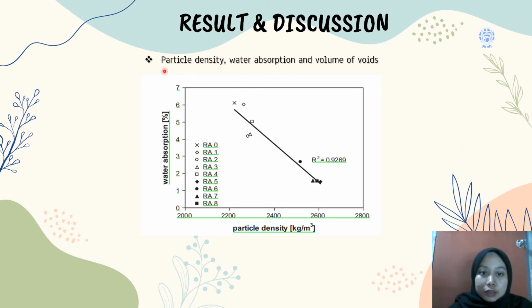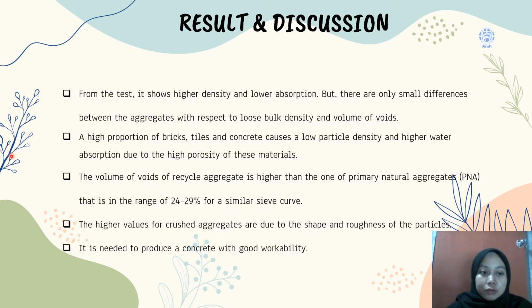And this is the result and discussion for the particle density, water absorption, and volume of voids. As you can see, this is the graph of the water absorption in percent versus the particle density in kilograms per cubic meter. As you can see, it decreases from recycled aggregate 0, 1, 2, 3, until recycled aggregate 8. From the test and from the graph shown previously, it shows higher density and lower absorption, but there is only one small difference between the aggregates with respect to loose bulk density and volume of voids.